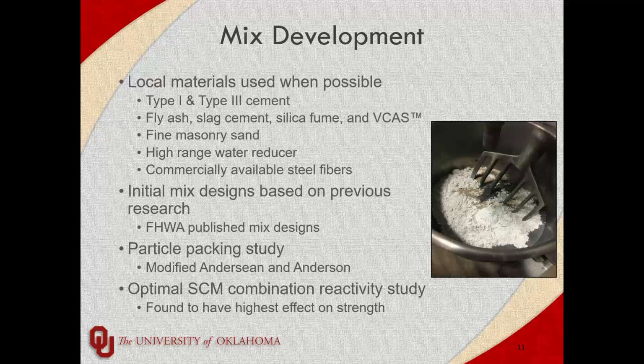But our next step was looking at particle packing, which is pretty common in UHPC mix design. The idea is to reduce the amount of free airspace inside of a mix. So you fill it with various sizes of grains from the different materials that you use. And because UHPC has such a low water to cement ratio, you actually use the cementitious materials in that particle packing as well, because not all of the cementitious materials are hydrated. Some of them remain dry, and they actually become kind of a pseudo aggregate inside of the mix.